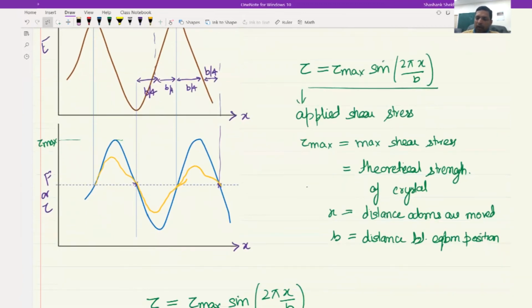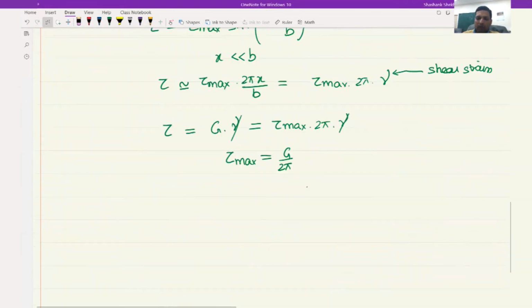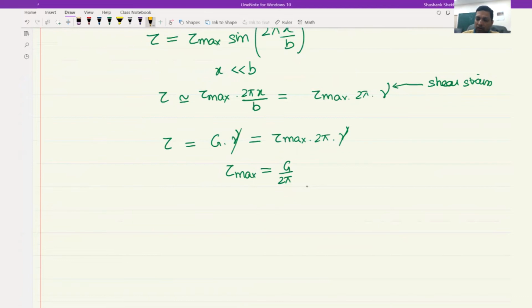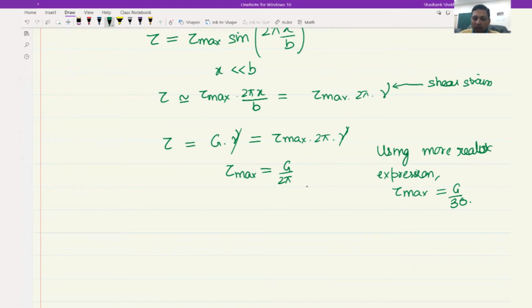And therefore there will be some variation, and based on that also people have calculated what should be the maximum shear stress or theoretical strength. People have found that using a more realistic expression, people have obtained that tau max is equal to G by 30. Okay, so this should be your, and this is approximately G by 6. So somewhere in the G by 6 to G by 30 should be your shear strength of the material.